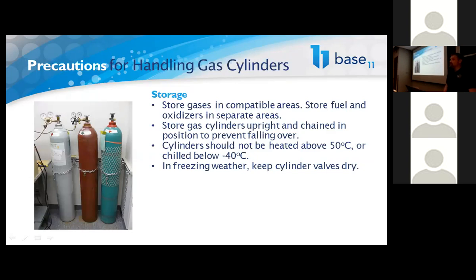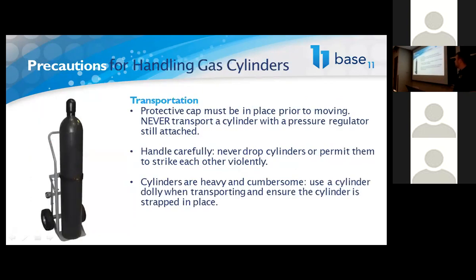The other thing that's really important is that any moisture getting into the valve can very easily interfere with its ability to seal properly, or it can actually plug the valve. And so if it's cold and wet, you want to make sure that the valves always stay dry. So when you're transporting them, as I say, always use a protective cap. Never ever transport it with a pressure regulator attached, because if it did topple, it's very, very easy to catch the regulator and that can shear off.